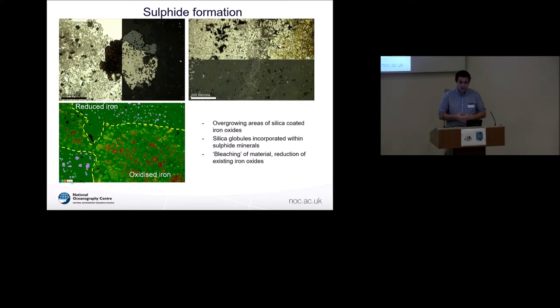We also have evidence of bleaching material. So the image on the right-hand side is within one of these iron-rich samples, and you've got iron-rich filamentous material on the right-hand side, but you've got almost pure silica on the left. So there's been some kind of fluid that's run through it. It's basically ended up reducing and remobilizing the iron in the system, but only on a local scale.